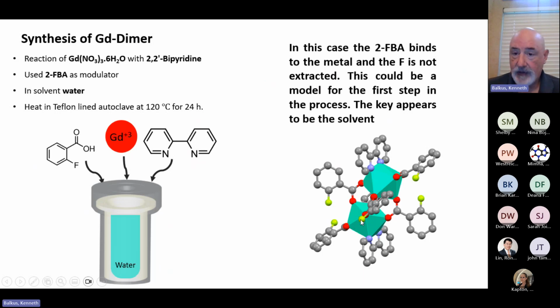Not surprisingly, we made a dimer. But interestingly enough, in just water with no DMF, you end up with the carboxylates of 2-FBA binding to this dimer. And so we look at this example in water as a model for maybe a transition step where the organofluorine compound first has to bind to the metal ion before it can extract off the fluorine.